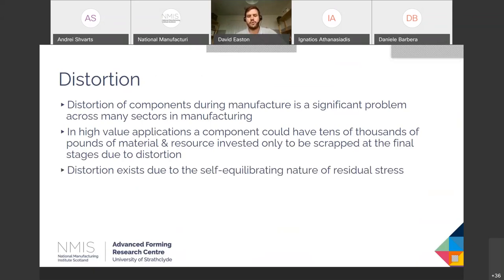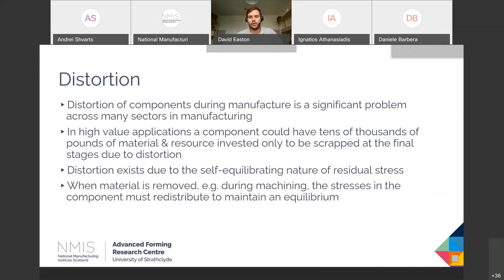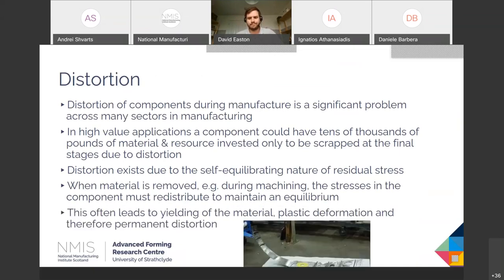And this distortion comes from that self-equilibrating nature that I'd mentioned previously. Throughout the part, all the stresses have to add up to zero, otherwise the part would be moving. So if we then remove some material, then we're removing the stress as well that existed within that region of the material. The part then has to redistribute all those internal stresses in order to maintain an equilibrium. In doing so, this redistribution can quite often cause the material to yield. You know, we get plastic deformation and the part is permanently deformed. As we can see here in that highly deformed sheet component.